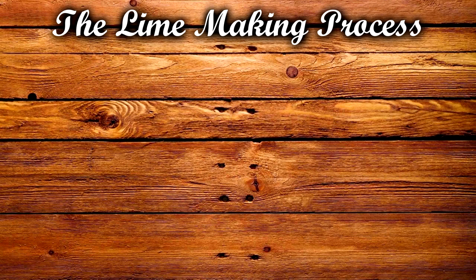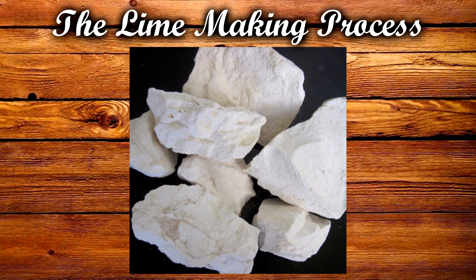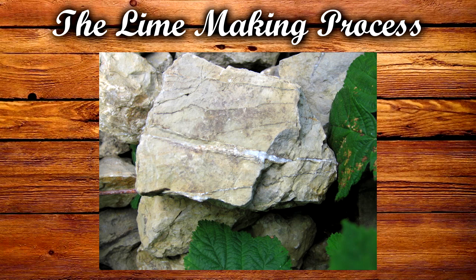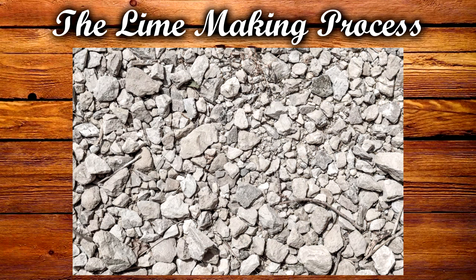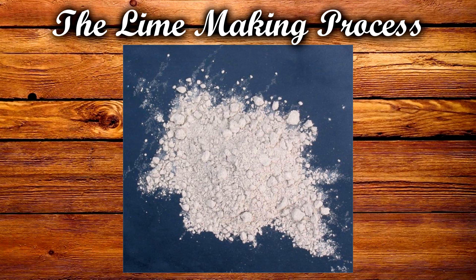Now it's time to talk about the process of creating lime from limestone. The limestone was usually crushed by hand into lumps of around 2 to 6 centimeters in size. If it was crushed too finely, it couldn't be used, as the fire needs gaps between the chunks to be able to breathe.